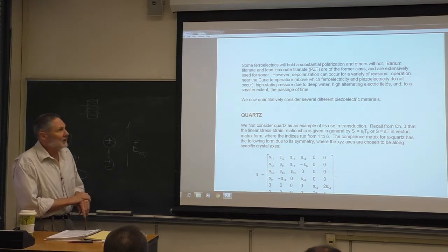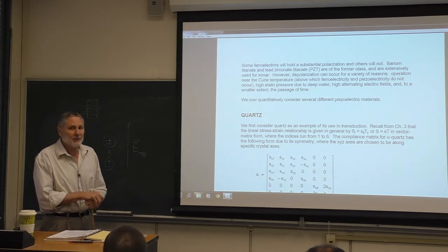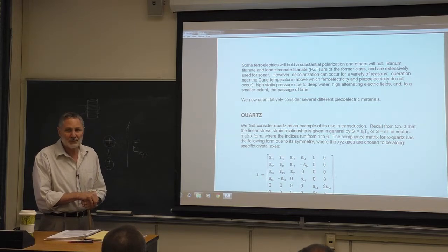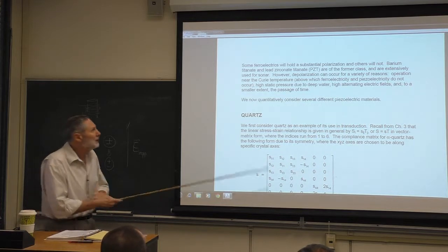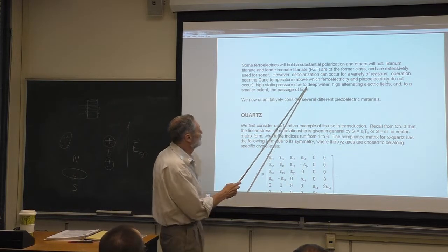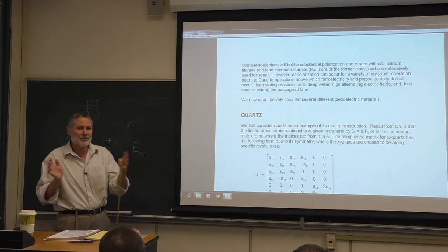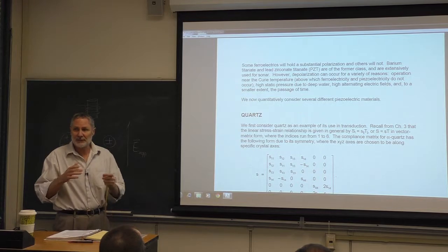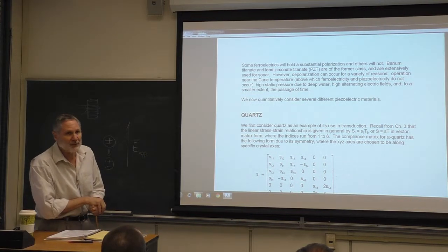Different ferroelectrics behave differently. Some, if you permanently polarize them, are fairly permanent. Now, like anything, if you abuse it, they'll start to depolarize. Some of you may be familiar with this on ships and submarines. We'll talk more about this later in the course, but you know what's coming here. If you overdrive it, for example, if you've got a sonar projector and you drive it too hard with an electric field, vibrating and sending out sound, you can start to get depolarization.